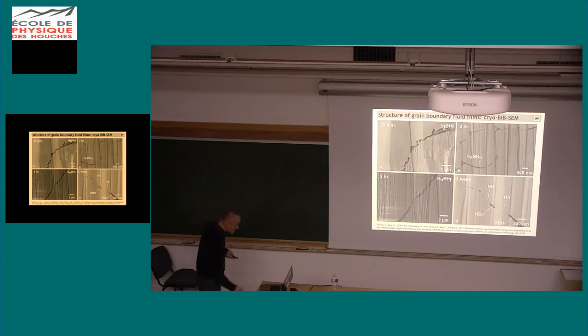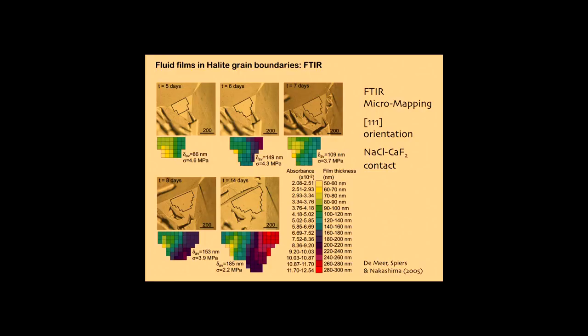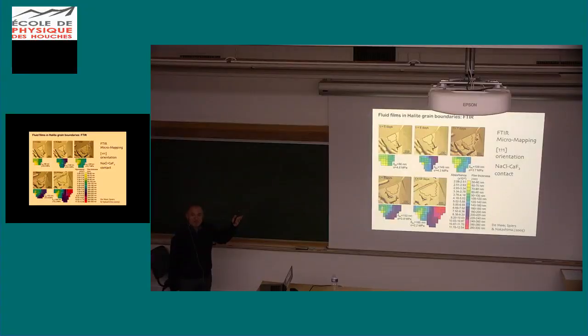Another beautiful example, and I put in quite a lot of examples of this grain boundary fluid film because not many people were convinced in the beginning that these films actually existed. This is a study by Cesar de Meer and Chris Spiers, who made these fluid films in a sodium chloride crystal pressed against a glass plate. So what you are seeing here, this triangular shape, is an actual fluid film of sodium chloride with a glass plate under stress.